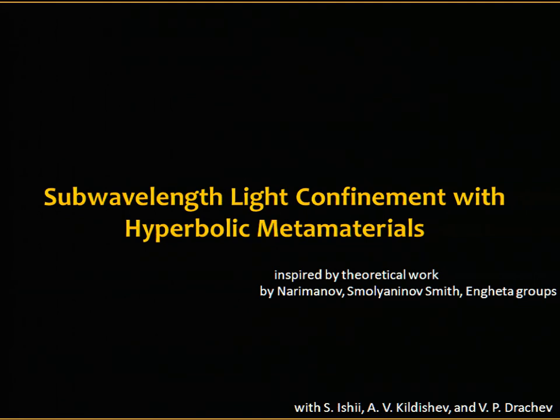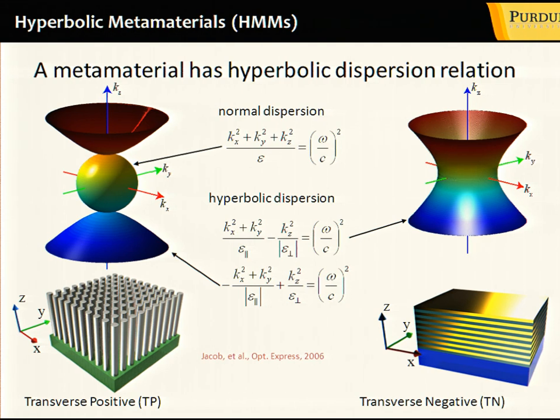So a few words about hyperbolic metamaterials. These are materials with probably the most promising applications, and that work to a large extent has been inspired by my colleague Evgeny Narimanov, and also his collaborative work with Smolyaninov, David Smith, and Engheta. So I will just show one particular work. What is special about these materials is that if you look at the isofrequency surface in K space for conventional dielectric materials, it's a bound surface, meaning that the K vector cannot exceed a certain number.